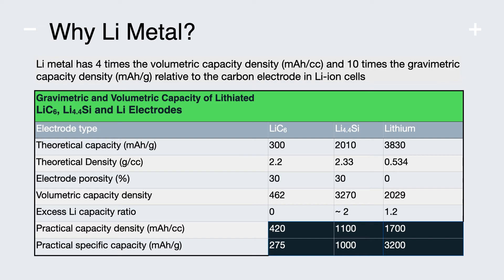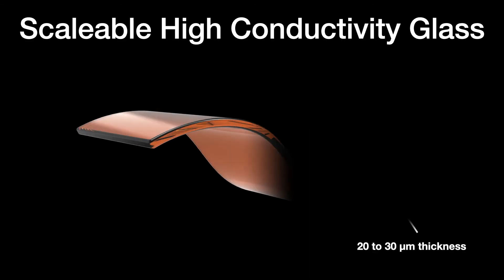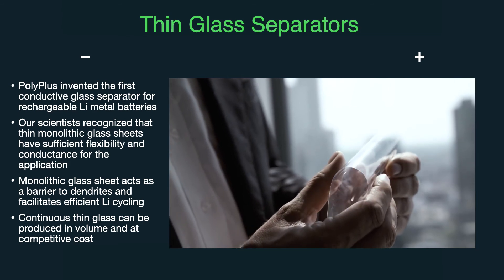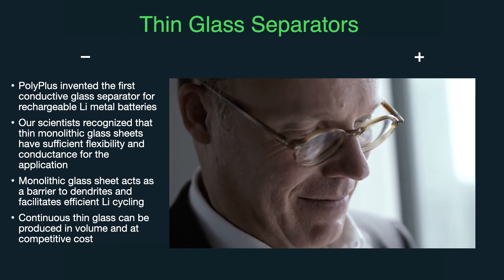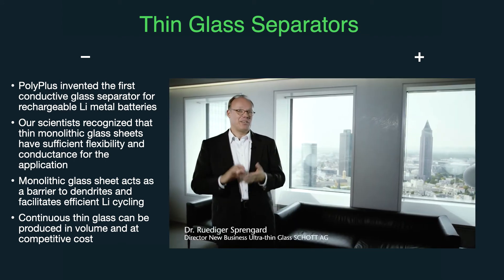That will have a big impact on applications that use batteries. So why glass? Why are we going to glass electrolytes? We are using a unique class of glasses — they're sulfides. They can be softened and molded in a very similar fashion to the way flat-panel TV screens are made, which is globally scaled. So this is an inherently scalable technology. We go down to very thin dimensions — 20 to 30 microns thickness. And when you do that, you get remarkable mechanical properties: here you see a scientist working with a 50-micron piece of glass, and it's behaving like a piece of polymer.